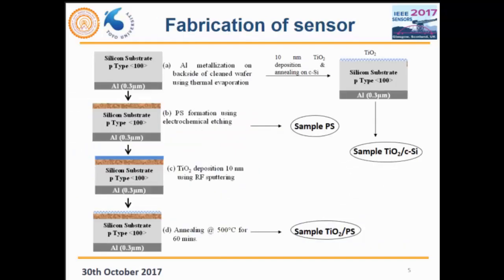How do we fabricate the sensor? It's a very simple process. We start with a silicon wafer; on the backside we do aluminum deposition to take it for an electrochemical process so that current can flow. We deposit aluminum as the backside contact, then take it through electrochemical etching which makes it porous silicon — almost 5 microns of layer in a porous network on top of the substrate. On this, we deposit TiO2 of 10 nanometers and then anneal it to form the more sensitive anatase phase. We also compare it with basic substrates: simple porous silicon and TiO2 on just crystalline silicon with no porous silicon in between.